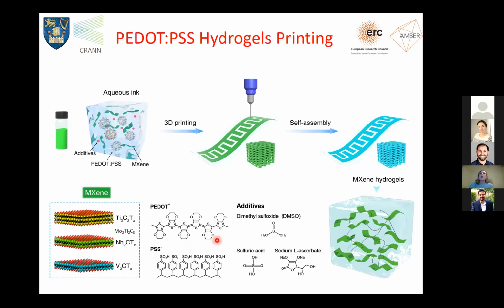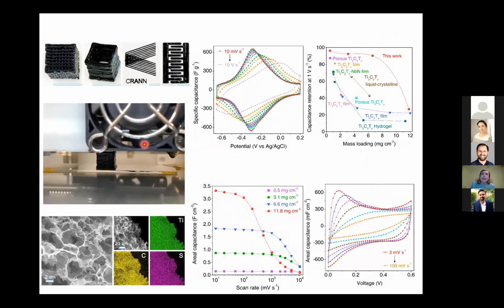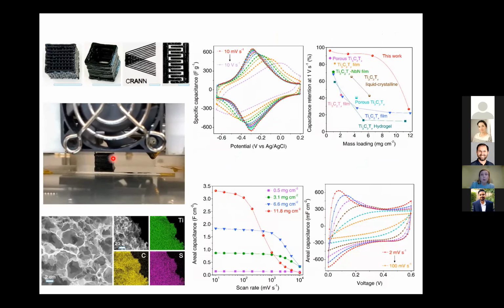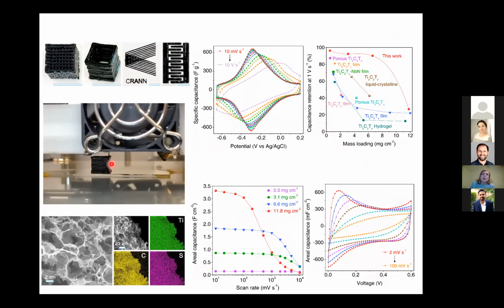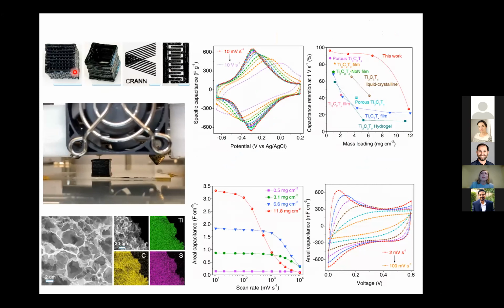More recently, we have also developed hydrogels based on MXenes and PEDOT-PSS, a conductive polymer. And again, we have managed to find the right formula using additives such as dimethyl sulfoxide, sulfuric acid, and sodium L-ascorbate to really give the right consistency to the hydrogels. And the beautiful thing again is that with that we can 3D print these gels into proper 3D structures. Here is an example of some of the devices that we can make, and we can achieve extremely high porosity and indeed a very, very good electrochemical performance.